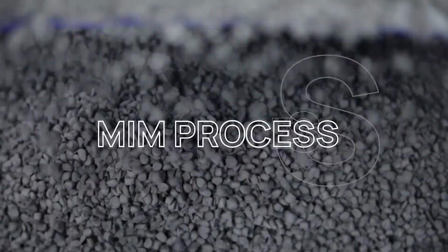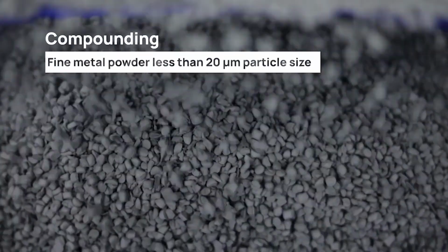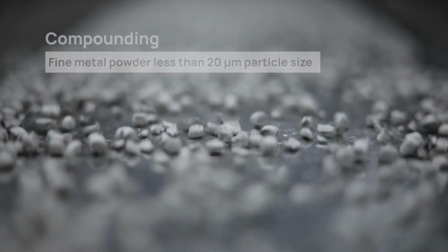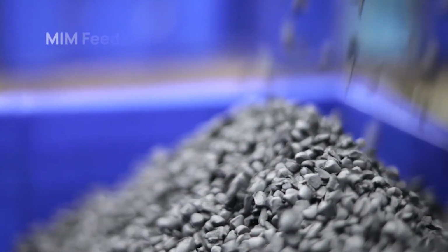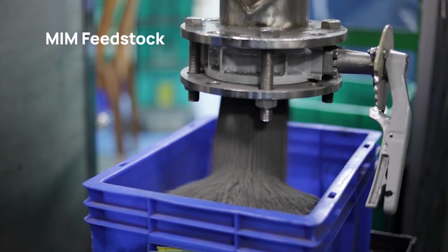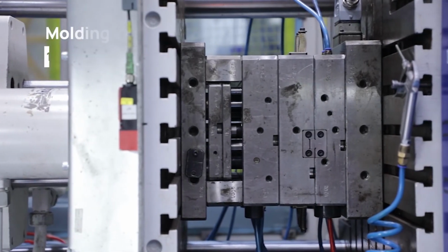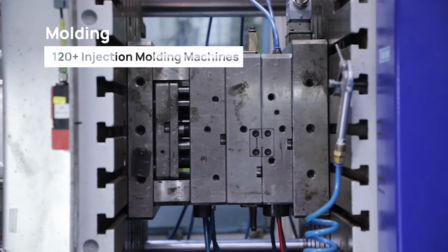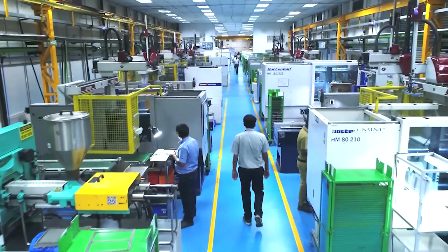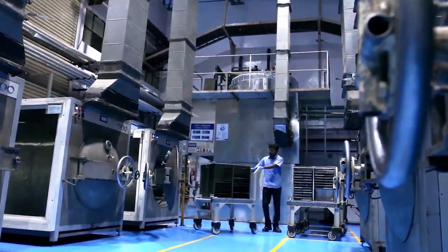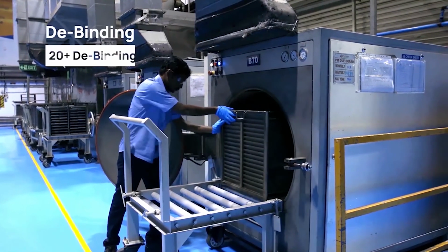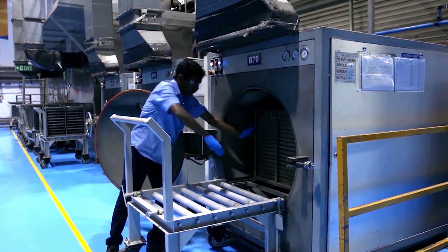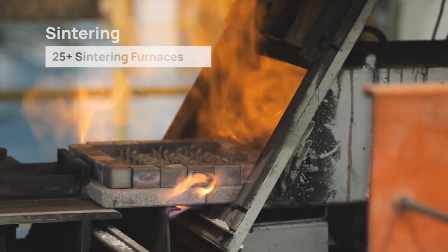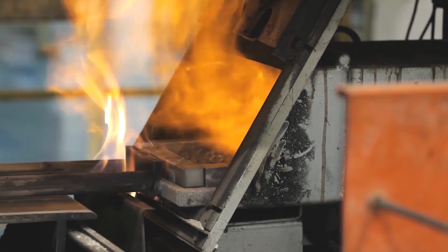The MIM process begins with compounding, manufacturing fine metal powder which is blended with thermoplastic and wax binders in proportional amounts to make the feedstock. The feedstock is injected in the metal mold to form the net shape at molding. After this process, the solvent extraction process is used for removal of primary binders at the debinding process. The last stage occurs in batch vacuum furnaces or continuous furnaces, to remove secondary binders and densify the component, which is coined as sintering.